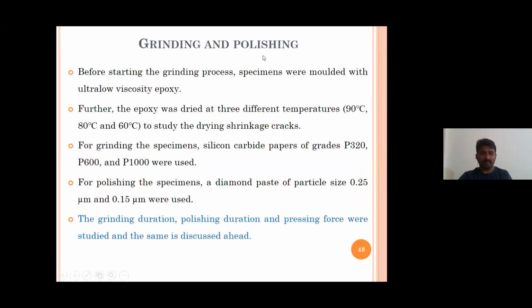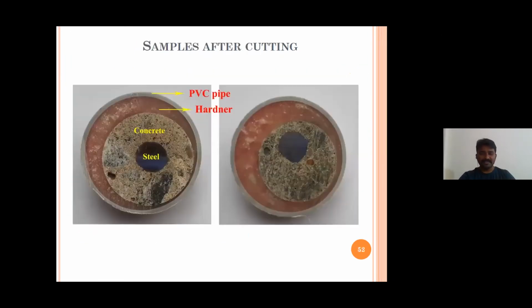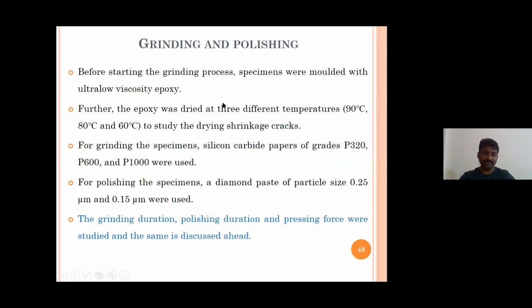So this is grinding and polishing. Before starting the grinding process, the specimen must be molded with ultra low viscosity epoxy. What do I mean by that? These were inserted in a certain liquid, ultra low viscosity epoxy, so that once I start grinding, the epoxy will go and fix in these holes or pores. As you can see here at the interface, we have a lot of pores. I wanted those pores to look bright black in our SEM images, so that's why we use ultra low viscosity epoxy.